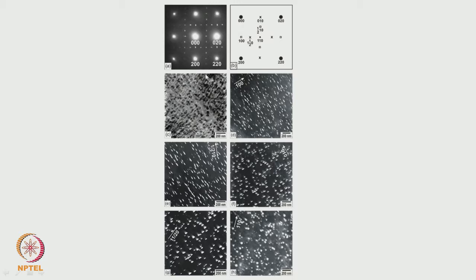But now if I look at this, one piece of information becomes very obvious. If I take it with respect to this 100 as well as with respect to half 10, which comes like this, this is half 10, this reflection. This reflection and this reflection, if I take it, it is essentially the same particles. So though there are two spots, they are coming from different spots of the same diffraction pattern, from the same phase. That is what you can identify.